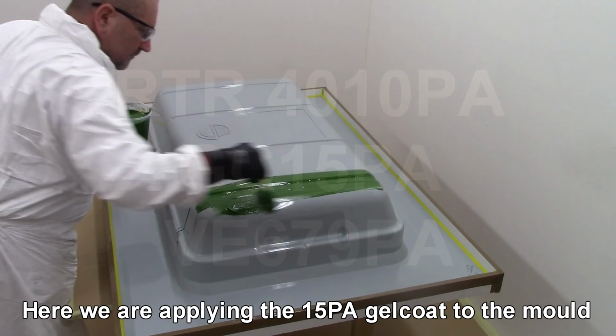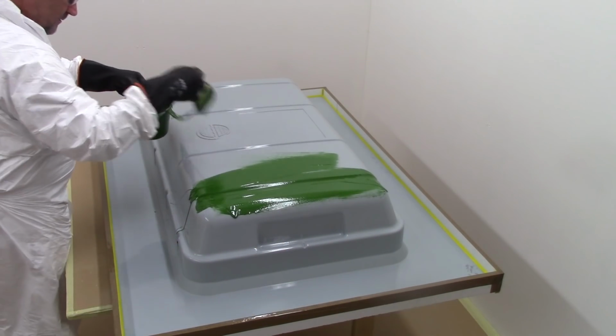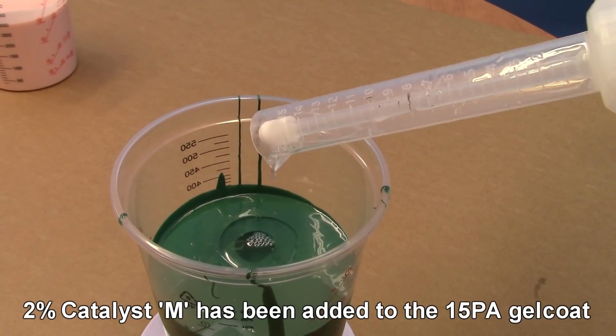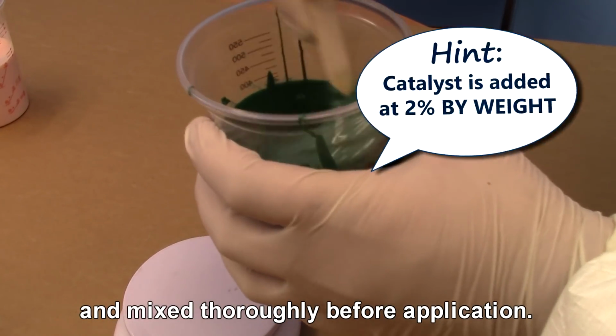Here we are applying the 15PA gelcoat to the mould. 2% Catalyst M has been added to the 15PA gelcoat and mixed thoroughly before application.